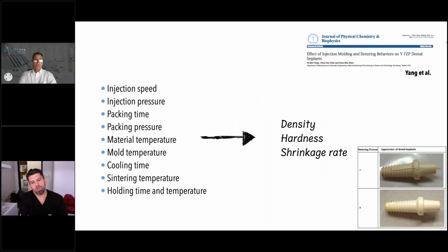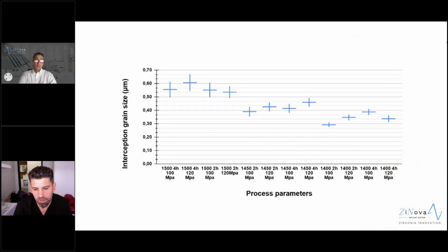And this secret sauce, there's a lot of elements that determine the density, hardness, and the shrinkage rate of the dental implants. All of these that you see here on the left can have an effect on the final product. One of the more important ones, perhaps, is the sintering temperature. A lot of the research goes into the amount of the temperature that is applied to the manufacturing process of these implants. And you can see here that we can play with different pressure, different temperature, different time, and you can see that the grain size will vary depending on all of these parameters.